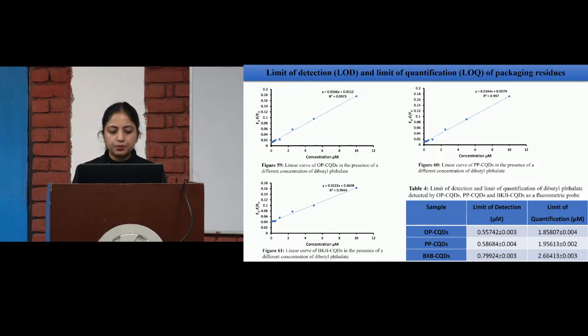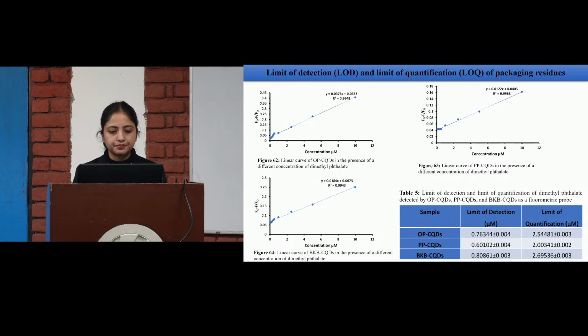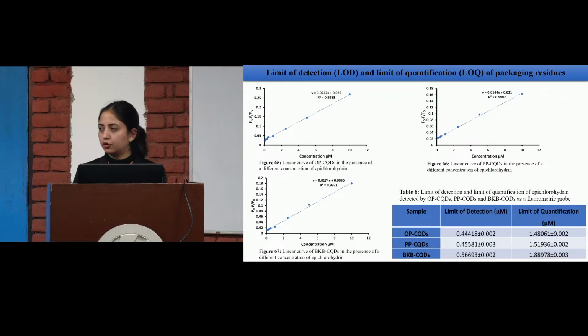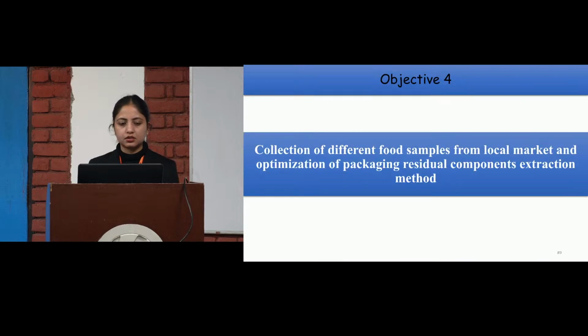So these are the least concentrations we can detect with our sensors. Then this is the linear graph of the onion peel, papaya peel and the broken kidney beans against the dimethyl phthalate, and this is against the epichlorohydrin. We can detect the limit of detection with the epichlorohydrin, that is 0.44418, 0.45, 0.56.